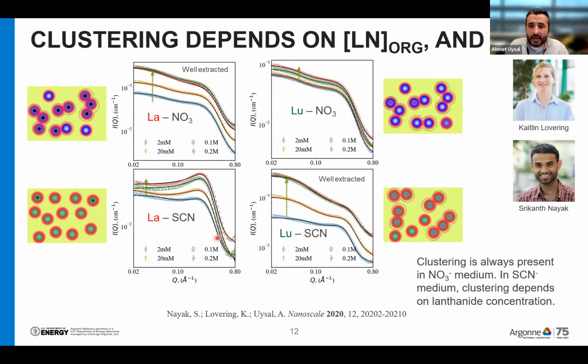But in thiocyanate, when we don't extract, the light lanthanides are not extracted, and we see this hard sphere structure that we have seen without any metal before. But if we extract lutetium, now we are extracting a lot of lutetium, and the structure changes. These aggregates now come together to form larger clusters. So the organic phase, the structure is changing in this case.